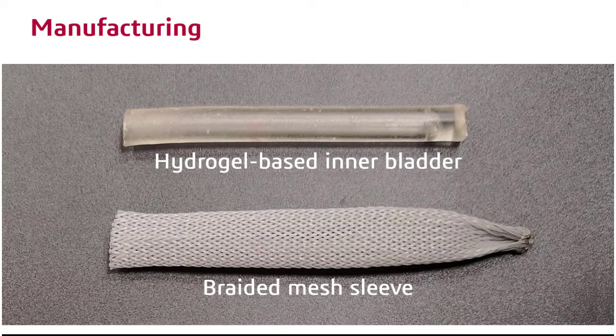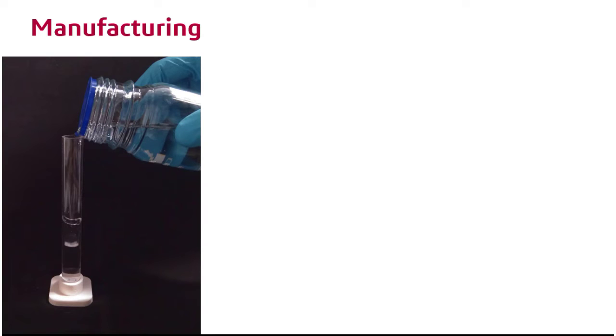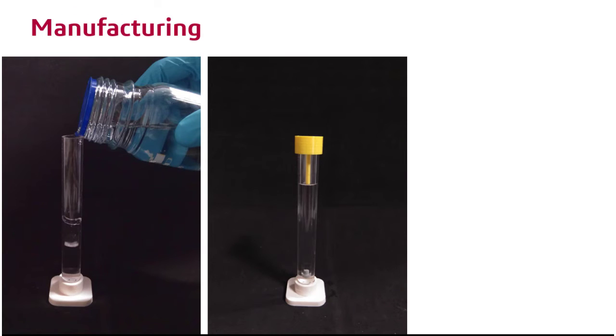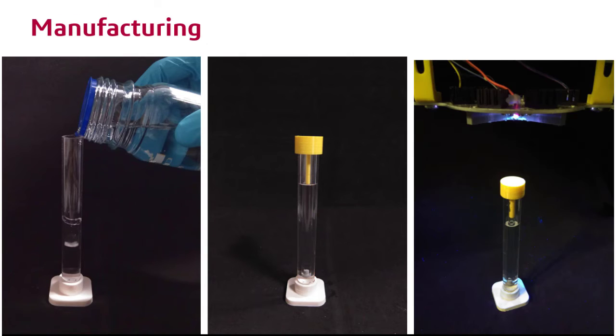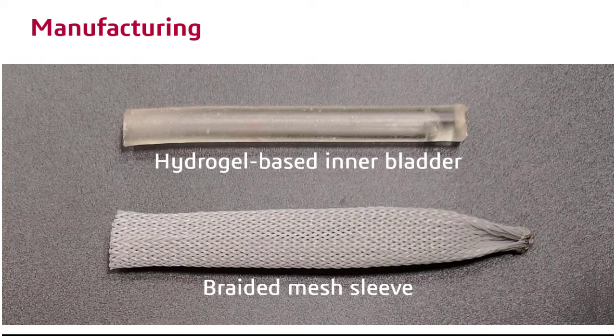Like the traditional McKibben muscle, ours consists of an inflatable inner bladder inside a braided mesh sleeve. The only difference is that our inner bladder is made of our equilibrated hydrogel. To manufacture this hydrogel bladder, we followed these steps. Firstly, the hydrogel solution is poured into a methacrylate tube. Then, a narrower tube is introduced inside the solution to form the cavity of the bladder. Finally, the solution is photopolymerized using a UV light lamp. Then, the bladder is removed from the methacrylate tubes and is left under ambient conditions for 1 week to reach the equilibrated state, like this one previously shown.